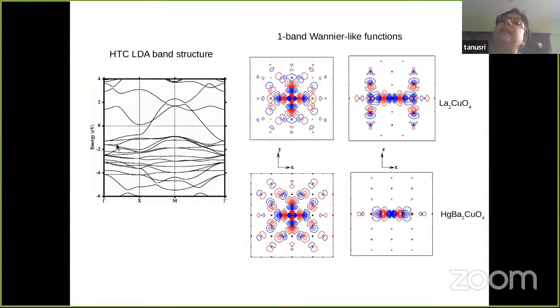And this is the DFT band structure of this compound. In any typical high Tc cuprate, there is a single band that is crossing the Fermi level, which is the zero of the energy. If you really look at the wave function corresponding to this single band, which is projected in two ways, namely the copper oxygen plane and the out-of-plane projection, what you see is plotted for the two compounds, namely the lanthanum compound and the mercury compound.